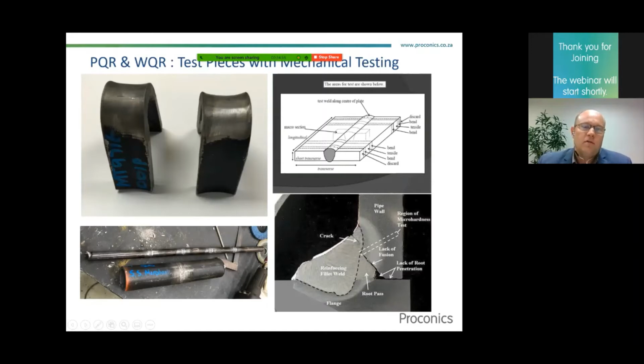The WQR stands for Welder Qualification Records. At the bottom left-hand corner, you will observe that there are two test pieces. The bigger test piece is to qualify the base metal range of the welder as well as process thickness. You also might want to qualify more than one process. Next to it, you will observe a smaller diameter test piece. This is to qualify the minimum diameter of the welder. On this one, you will observe that there are 4 weldments in this test piece. The reason for this is, in accordance with ASME Section IX, the weldment to be tested needs to be 150 millimeters long.